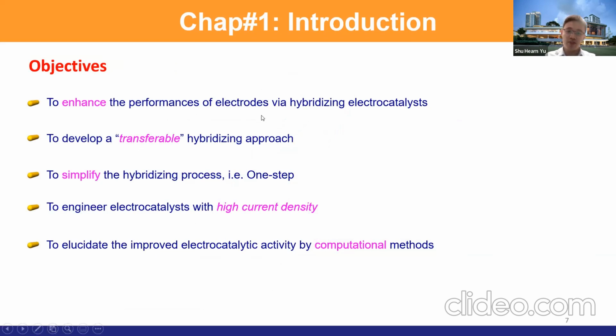So to enhance the performance of the electrode via hybridizing electrocatalyst, to develop a transferable hybridizing approach. Transferable means I can apply this method in this system and also another catalyst system. So this method is more like a universal method. To simplify the hybridizing process, maybe one step or two steps at most, to engineer electrocatalysts with high current density, because many catalysts are very active, but they are meant to be tested at low current density. At high current density, maybe they suffer from stability issues, or the sample could detach from the supporter.